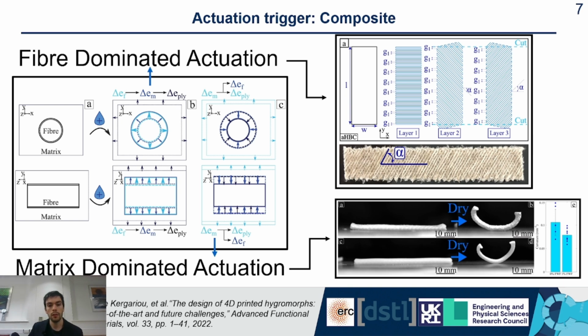These concepts are different because in the fiber-dominated actuation, the humidity triggers the deformation first of the fiber, and then the fiber expands and contracts, and then pushes and pulls the matrix, and this creates the overall deformation of the layers, and therefore of the entire structures.